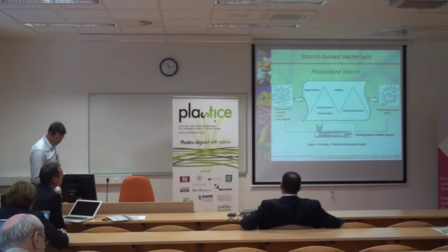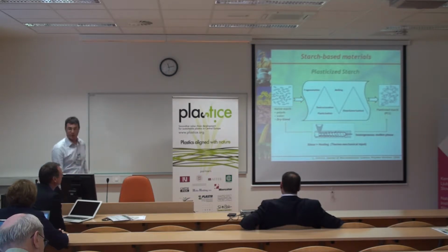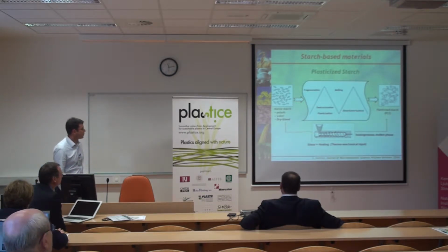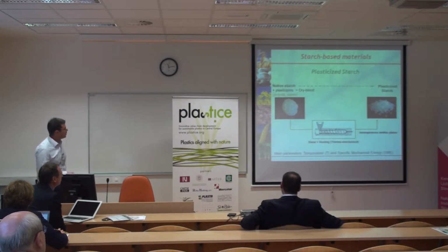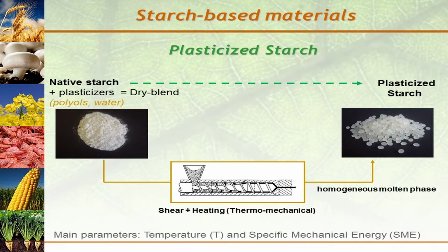homogeneous molten phase. And by controlling the shear and the temperature, we obtain plasticized starch, trying to avoid the depolymerization or degradation of the starch. So here, that's the powder. We start with the dry blend, and then we recover the plasticized starch as pellets that we can then process again, blend with other materials, characterize and so on, as we will see just after.